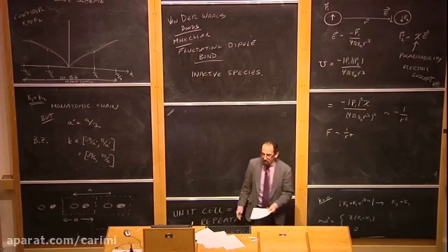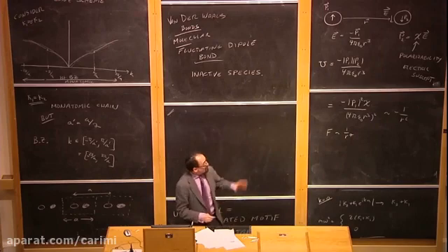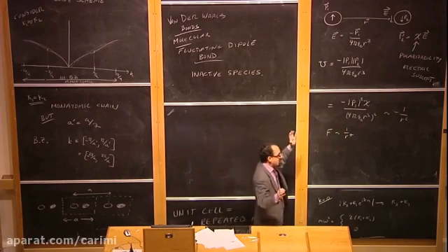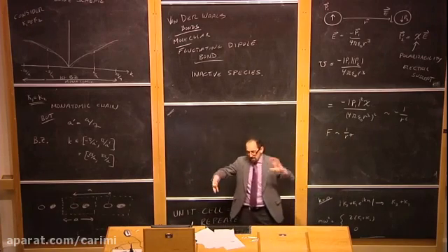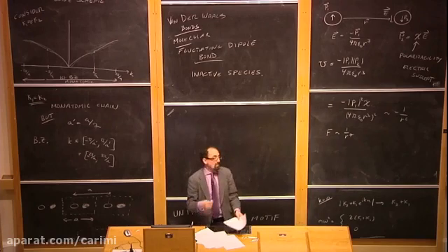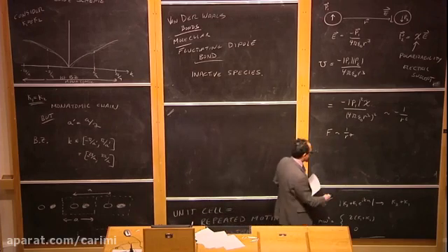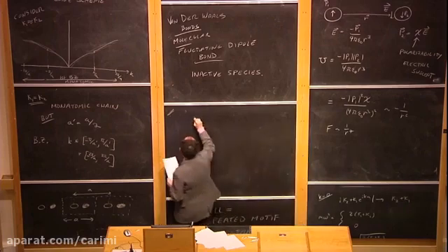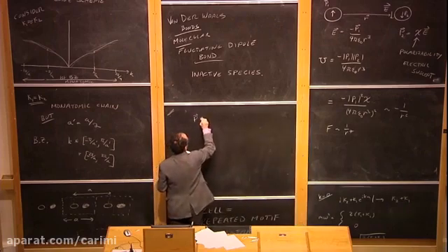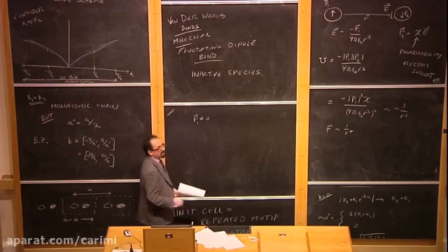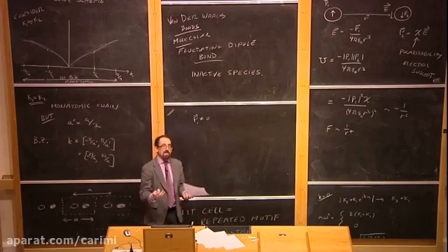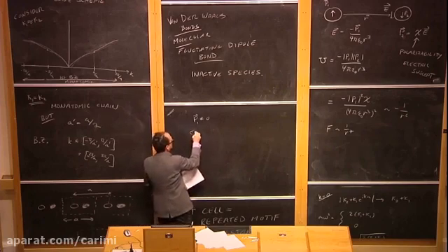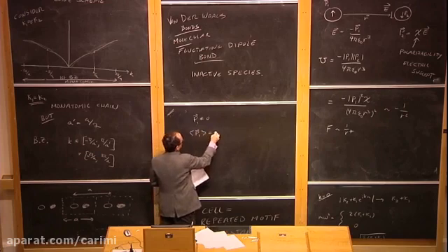Now, that's more or less how the calculation goes: you have a polarization in one atom, it induces a polarization in the other atom, and the polarizations attract. But you might say, well, wait a second. This whole argument was predicated on the statement that the polarization is not equal to 0 to begin with. But in a spherically symmetric atom like helium, the expectation of the polarization is 0.